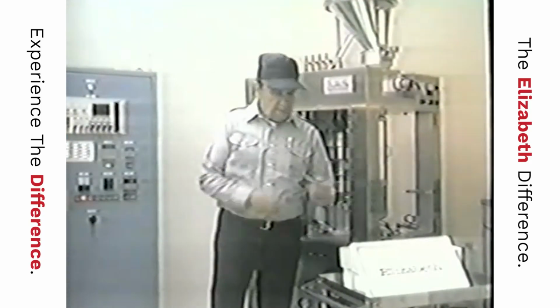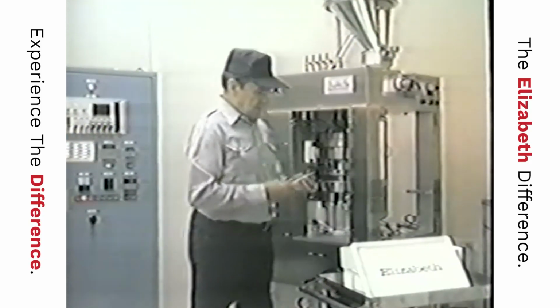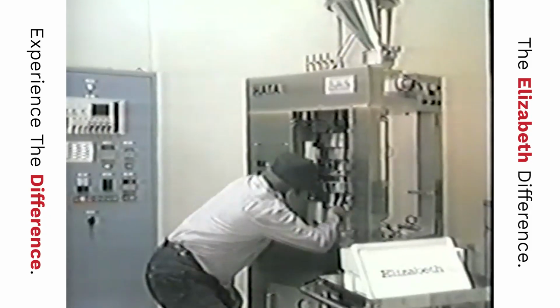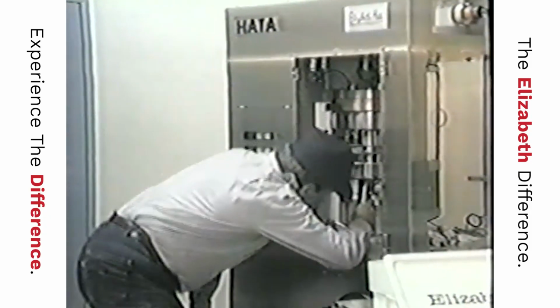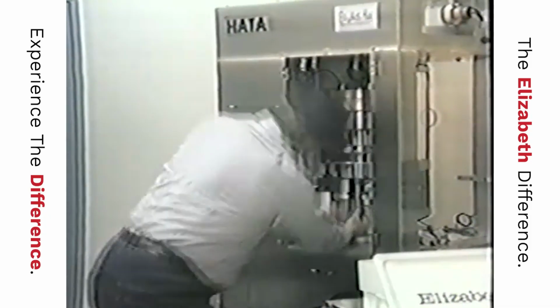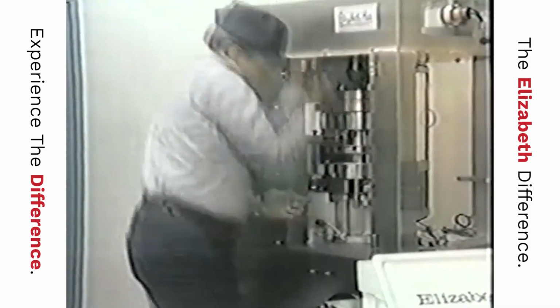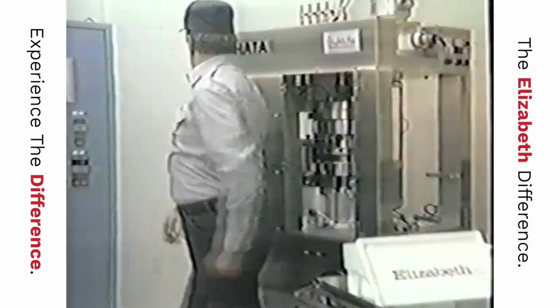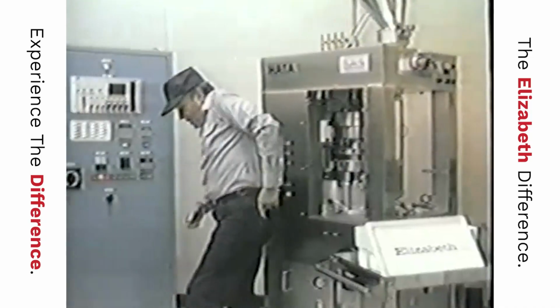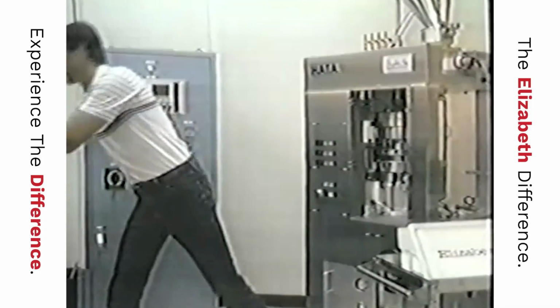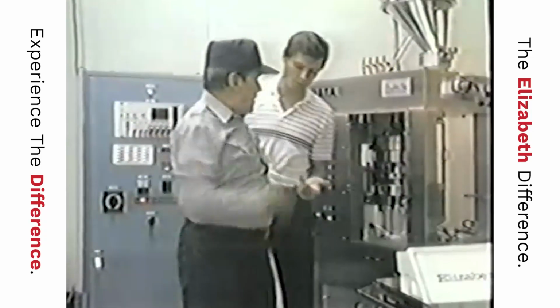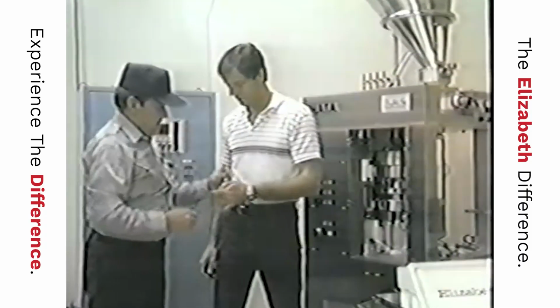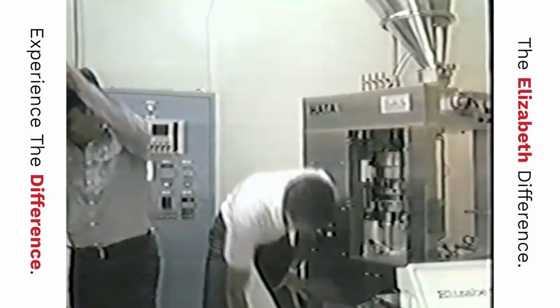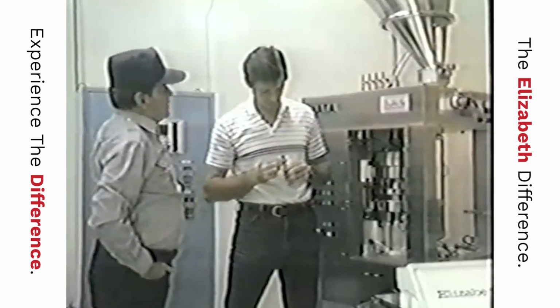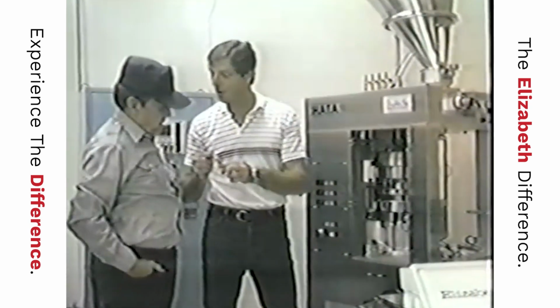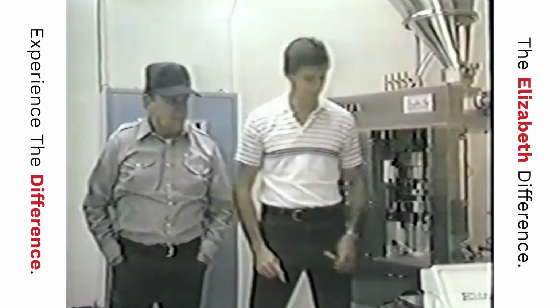The same care should be taken when inserting the lower punches. Large capsule shapes, such as the one shown here, have a tendency to bind in the punch socket if they're not inserted easily into the center of the punch guide. This binding not only causes nicks in the punch tip from misalignment, but also may raise burrs in the punch guide, which in turn will put scratches in the punch barrel. These scratches may also cause additional problems because they tend to pick up material, which results in binding. And here you can see what can happen when proper setup procedures are not followed.